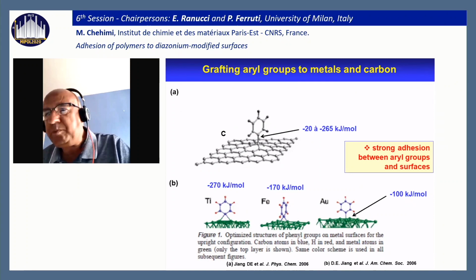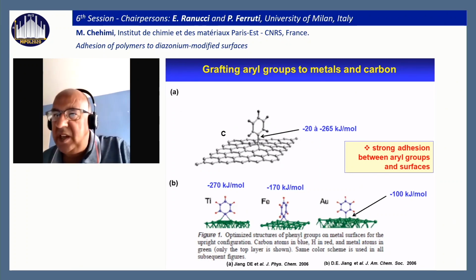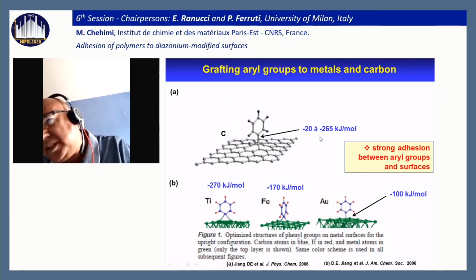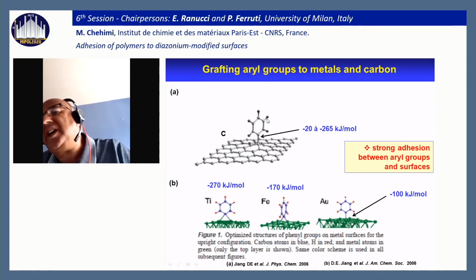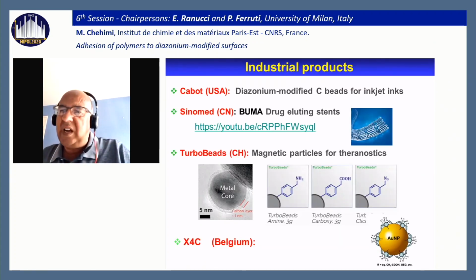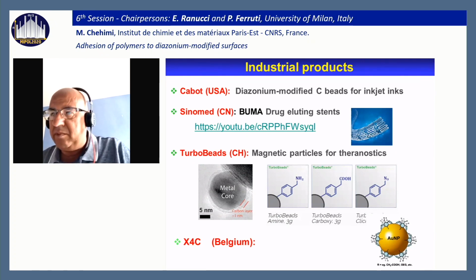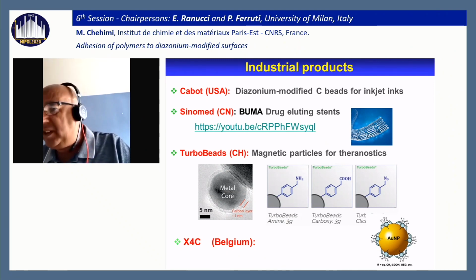By DFT, it is now proved. The calculation proved this, in the work of Jiang in the United States. They proved very strong adhesion bonding between the aryl groups and the carbon, and they have done that on carbon, on graphene-like sheets, but also on metal surfaces. Because the aryl surface bonding is very strong, this led to a lot of industrial developments, and the best known of them are